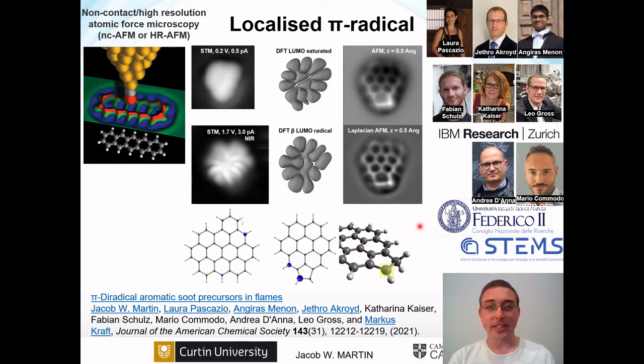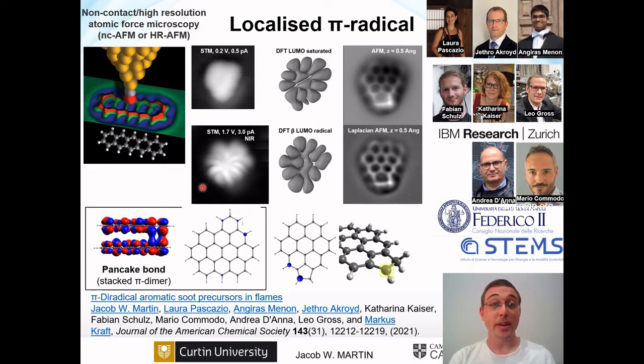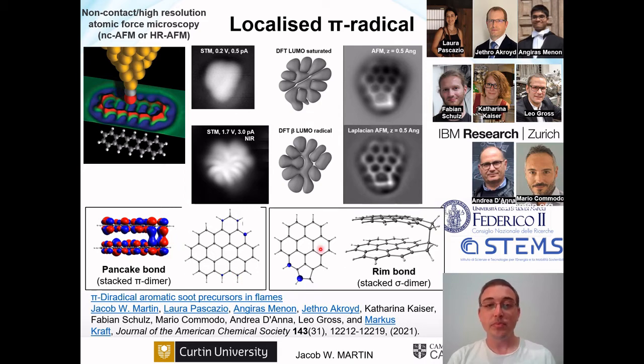Now, we know about aromatic radicals, and most aromatic radicals are this type, and these are unreactive. They do form some bonds when they're stacked, what's called a pancake bond. This is a multi-center bond, but this is not stable in the flame. Whereas we found that these localized pi radicals on these specific sites form very strong, so flame-stable bonds. We call them rim bonds because they are quite unique in that they bond around the rim, and they also allow stacking to occur. So this is a new type of aromatic bonding that we found.